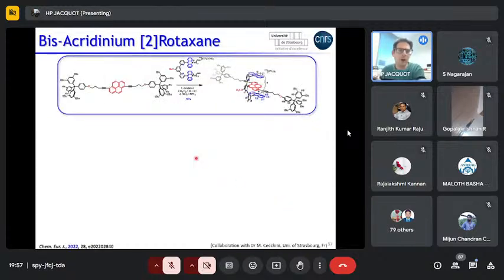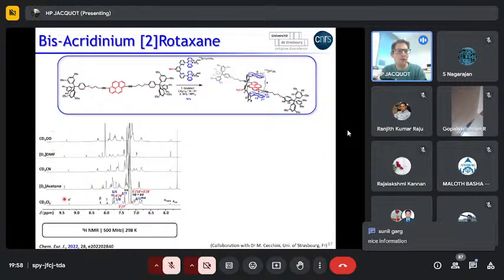So in our case, what we've done is that we started from a dumbbell having a pyrene recognition site, and then we did a clipping strategy, and we got the [2]rotaxane in a decent yield of 18%. What was fun with this molecule is that it's soluble in a variety of solvents, from DCM to methanol. What you see for this molecule in the different solvents is that you have almost the same chemical shift for most of the protons. So this means that they are in the same environment. And this clearly suggests that we have the macrocycle in the vicinity of the pyrene recognition site.